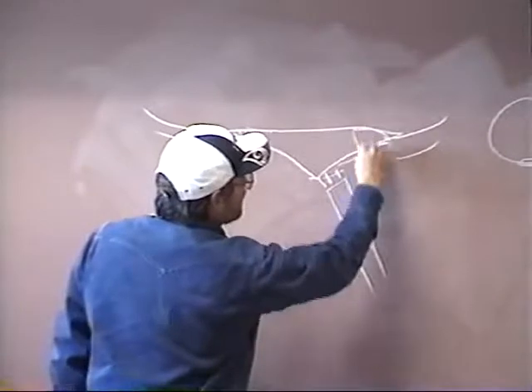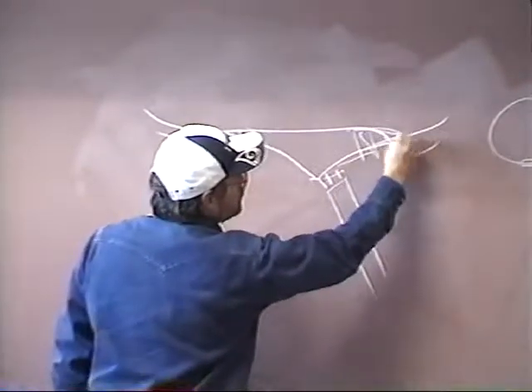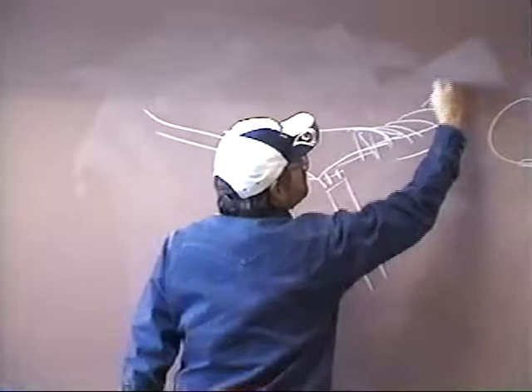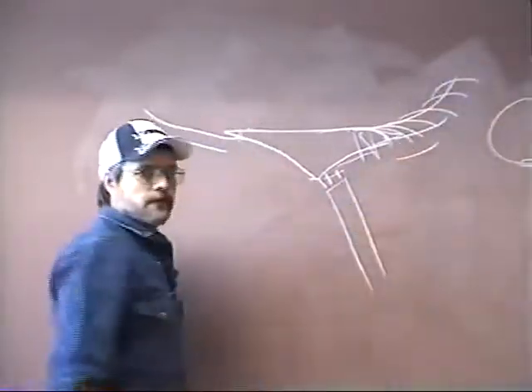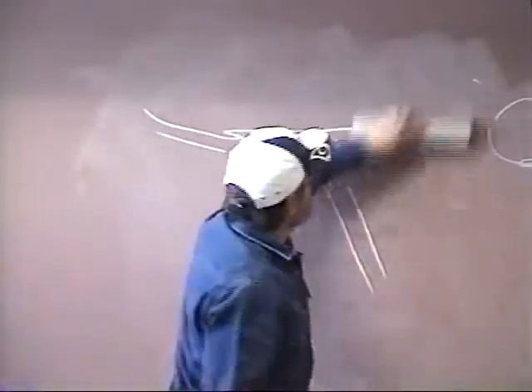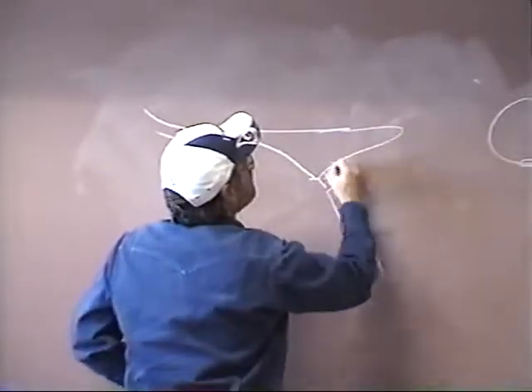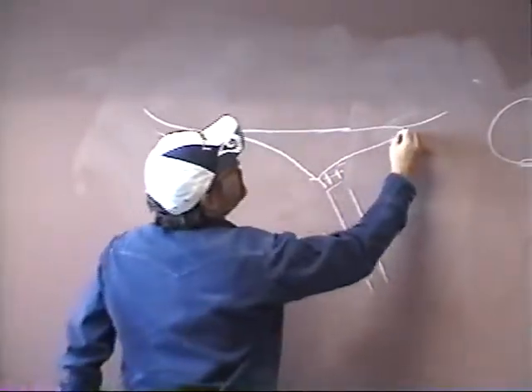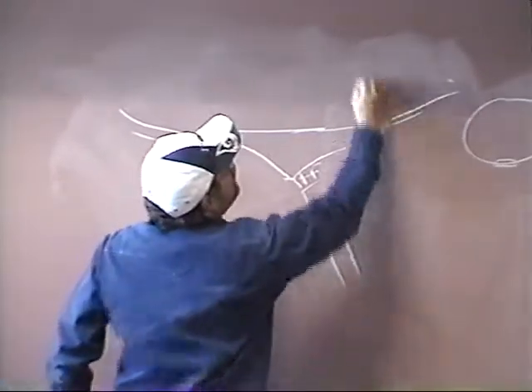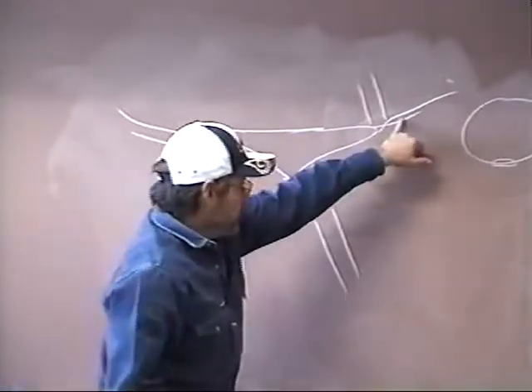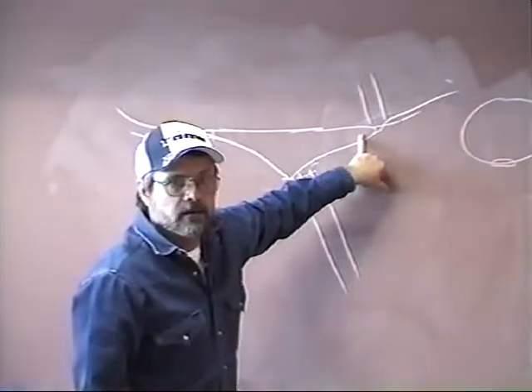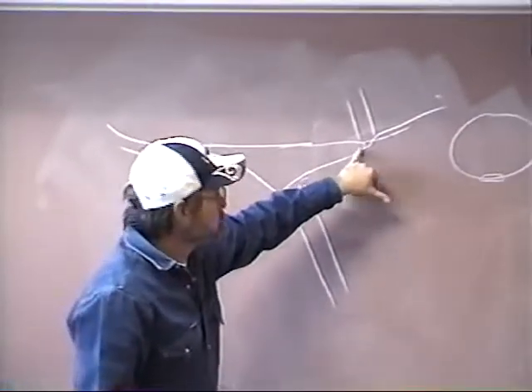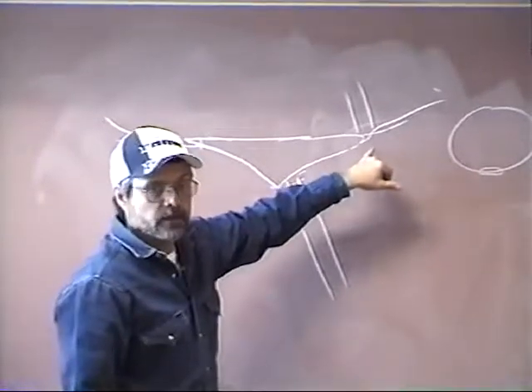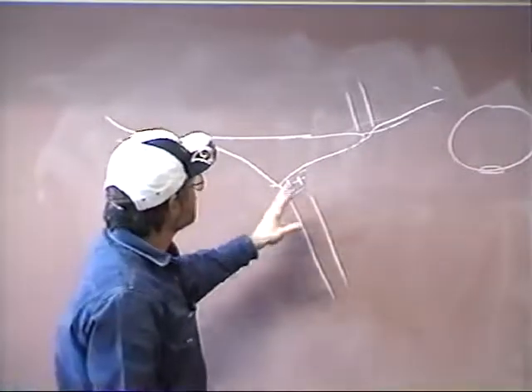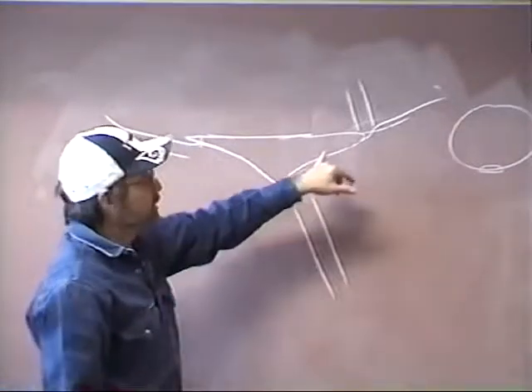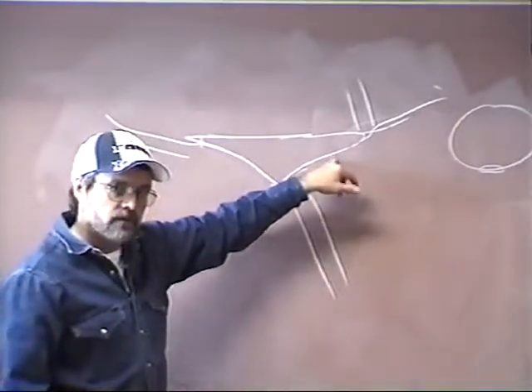So if you can burn through that tack back up over here, then as you continue, you're going to have a smooth transition into your weld. If you don't, if you come out too fast, and you don't burn through the end of that, you're going to have a skip. You're going to have a spot right there where your weld didn't tie into your tack. We call those toenails. And this right here is the biggest problem that people learning how to pipe weld have. So you want to make sure that you grind this properly and that you burn through the tack before you reach the end of it.